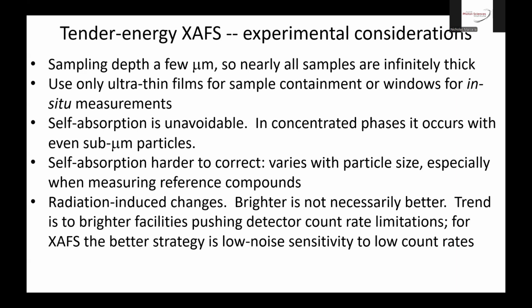And it will vary with particle size, so it makes it harder to correct for. It's not like it's infinitely thick, then you apply a self-absorption correction. This is in between, it's always in between. So you've got a variable amount of self-absorption, even grain to grain within a sample. And so it's really hard to work with. You just have to be aware of it and work around it wherever you can.